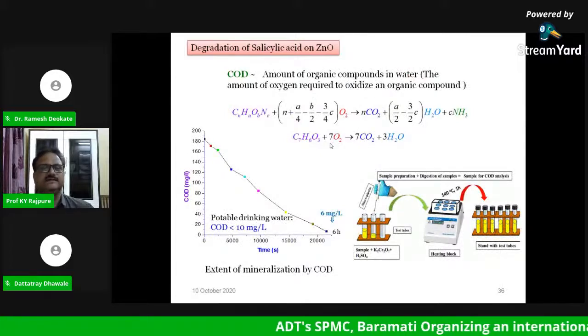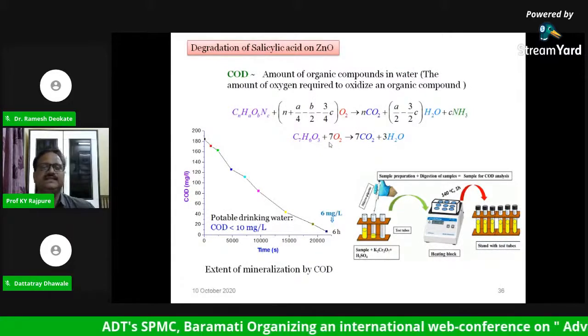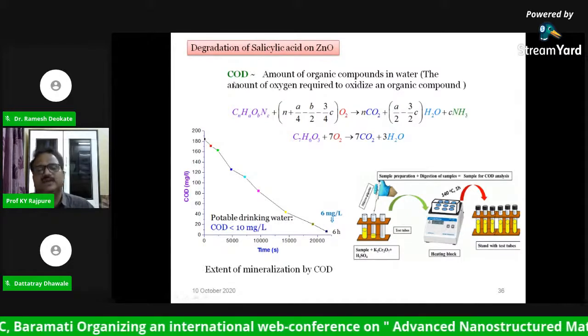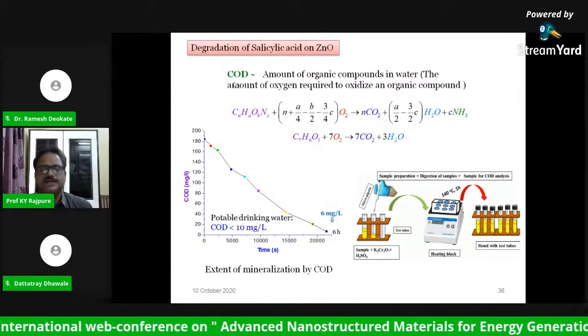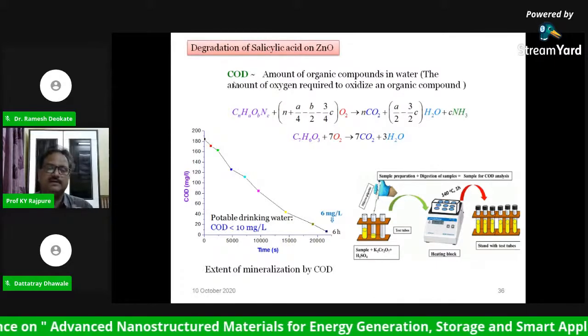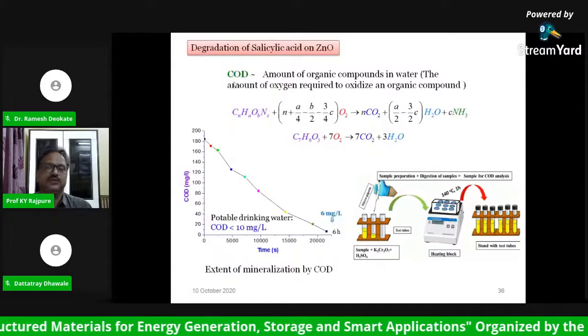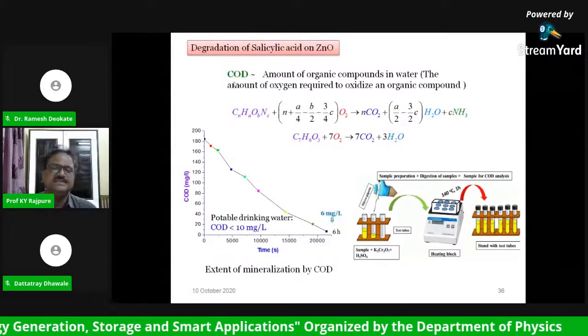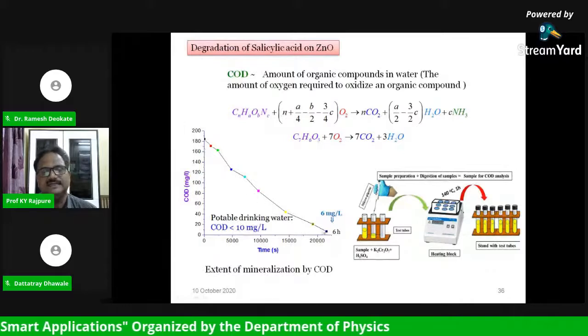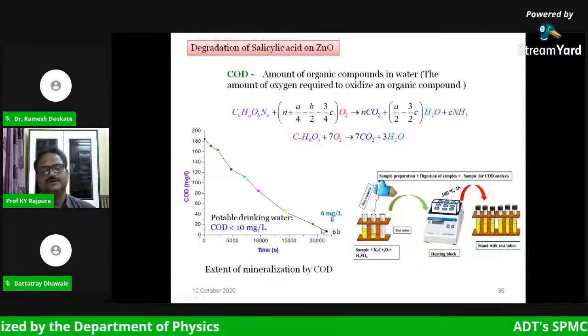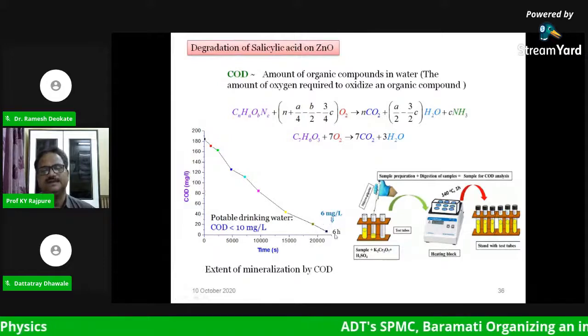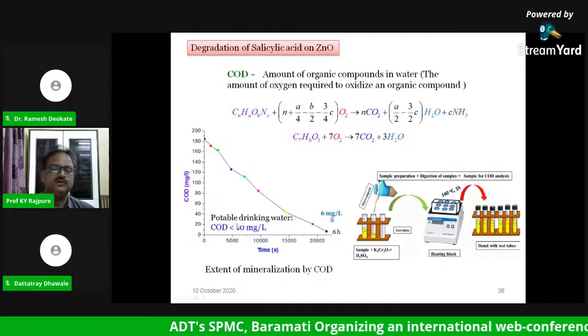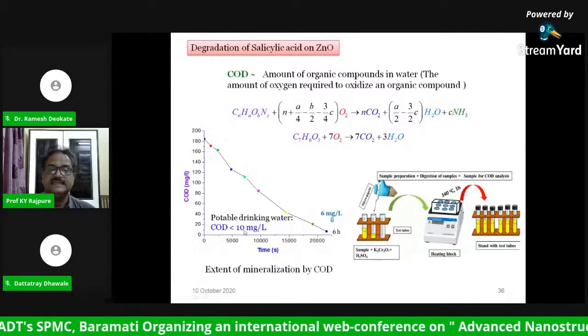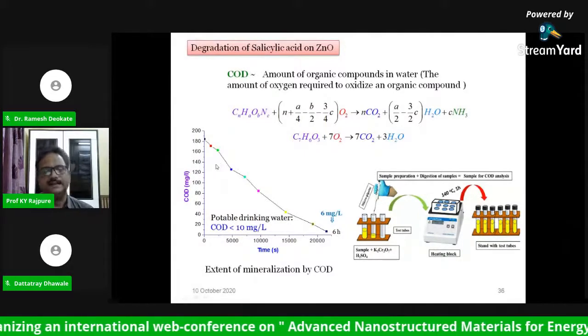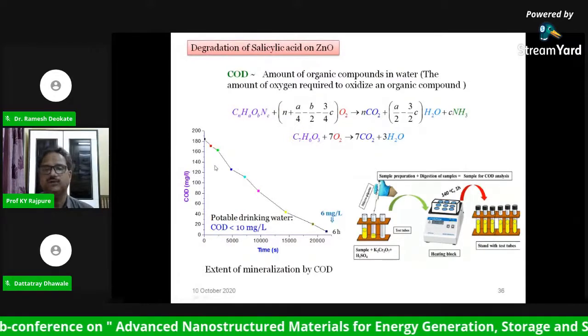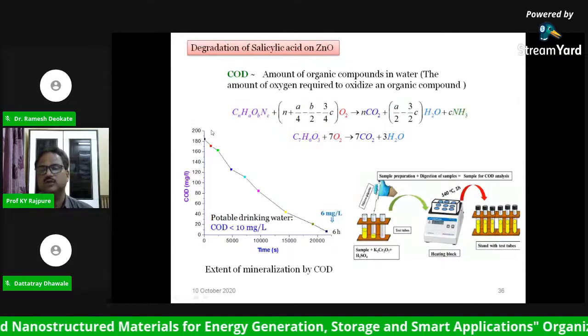These are the results on salicylic acid, where the chemical oxygen demand, COD, is proportional to the amount of organic impurity or organic chemical present in the polluted water. So if COD decreases continuously, it means the amount of organic matter continuously decreases, which means it degrades. So it is possible to achieve a COD of the order of 6 mg per liter after 6 hours. We know the COD of potable drinking water should be less than 10 mg per liter. So it is possible to get potable drinking water out of polluted water with the help of this photocatalysis, photoelectrocatalysis.